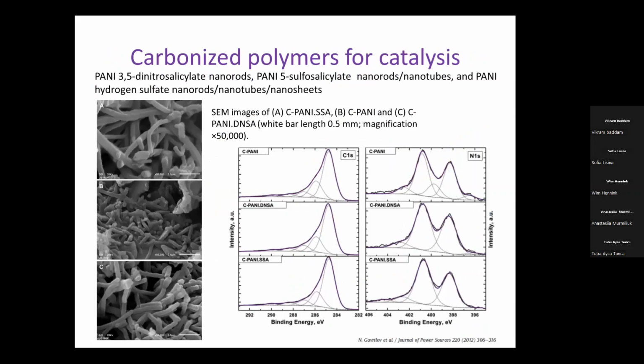A case of, again, carbonized polyaniline, this time for electrocatalysis. So you saw some examples of the same materials used for electrochemical capacitors. And now we use it for electrocatalysis. This proves that these carbon materials are really versatile. So we can see that morphology is largely preserved. So we have nanorods, nanotubes, nanosheets, depending on the morphology of the precursor.